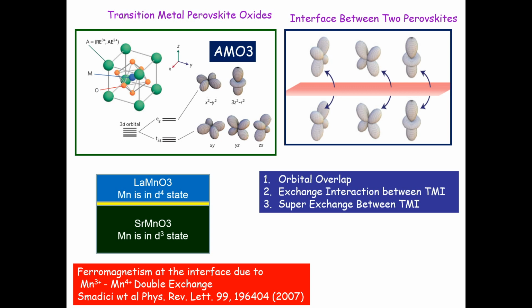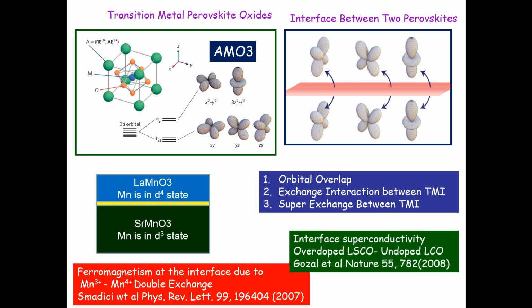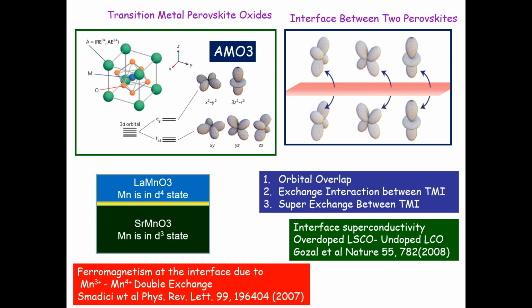You can also produce novel phases in the case of high Tc oxides. For example, if you take a non-superconducting lanthanum strontium copper oxide in the overdoped regime, and a completely undoped La2CuO4, both are non-superconducting, but if you make a very clean interface between the two, there is superconductivity at the interface. So it's another interface phenomenon.